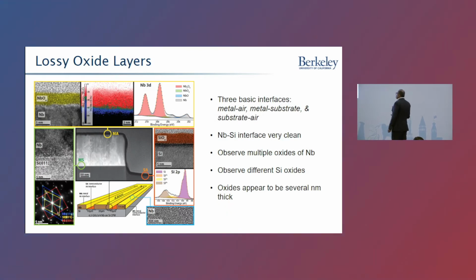Let's start looking at that niobium surface, in particular after we process those wires. Here is a microwave structure. This is niobium sitting on silicon. On the niobium surface, you can see there's the niobium metal, and then this yellow stuff on top, which I call NbOx, telling you that we have, in fact, all the different stoichiometric combinations of niobium oxide. This is a high-resolution transmission electron microscope image. If you now do XPS, scattering measurements, you will see which parts are NbO, which parts are NbO2, and which parts are Nb2O5. They give decoherence in different ways. Some are semi-metallic, some are reasonable insulators, and so on. This color map tells you that we have a lot of Nb2O5, a particularly bad actor in this game.